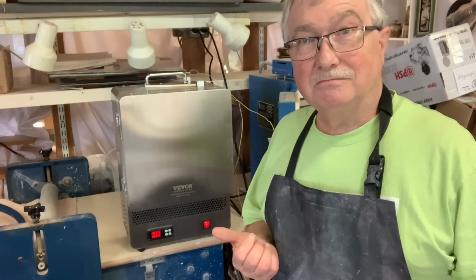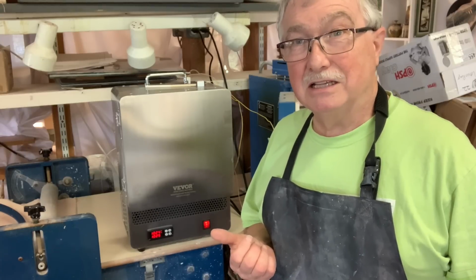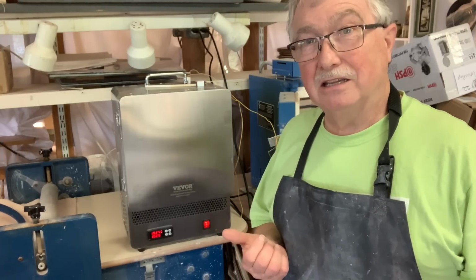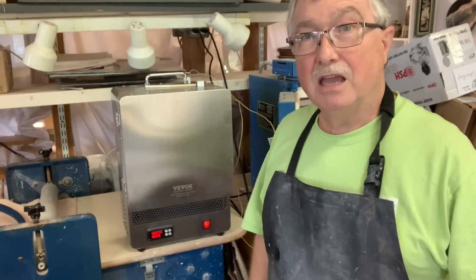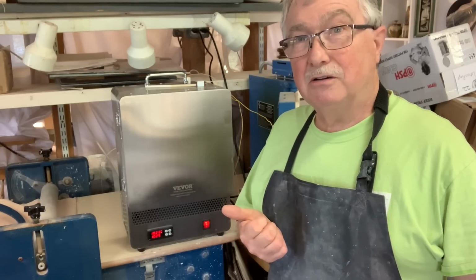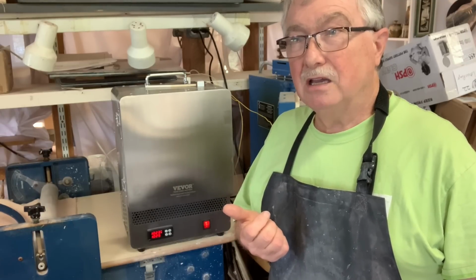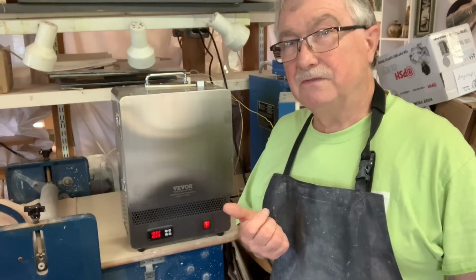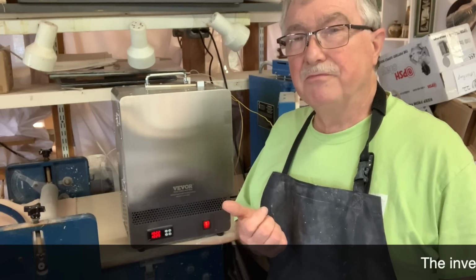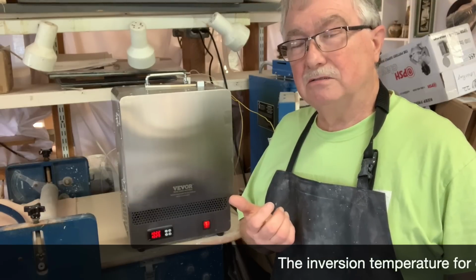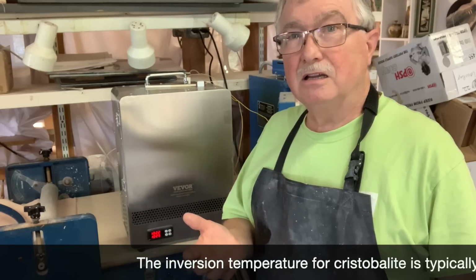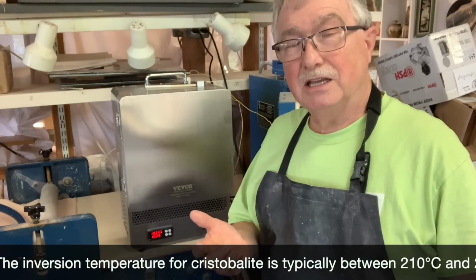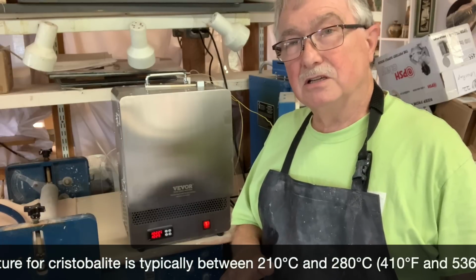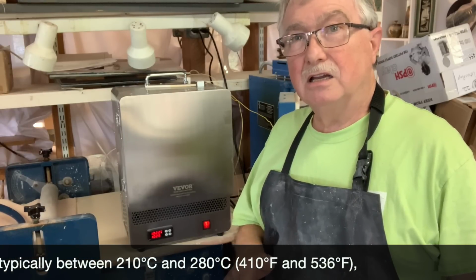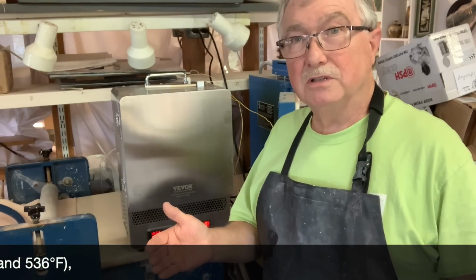Is your pot going to survive if it's bisque fired that fast? That will be the next firing that I'm going to do, because I have a piece ready to get in there, and I'm going to put it in and let it do its thing. There are two things that I have to be aware of, because at about 425 degrees to 450 degrees Fahrenheit, which is about 250 centigrade, there's a cristobalite change in the clay body that you're supposed to go through slowly. And again, you're supposed to do it at around 600 to 650 centigrade, and you're supposed to go through that period slowly too, because the clay changes chemically and loses its water and things like that.